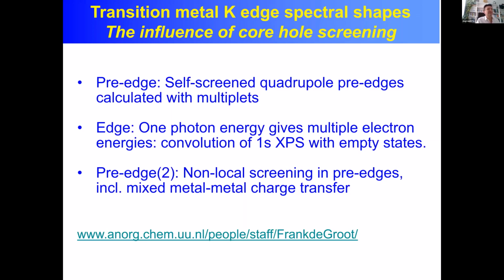In copper 3+, it's a little bit different, and also iron 4+, or anything which is what we call a negative delta system. So when the charge transfer energy is negative, in copper 3+ the third hole goes to oxygen, so you can also call it oxygen minus.